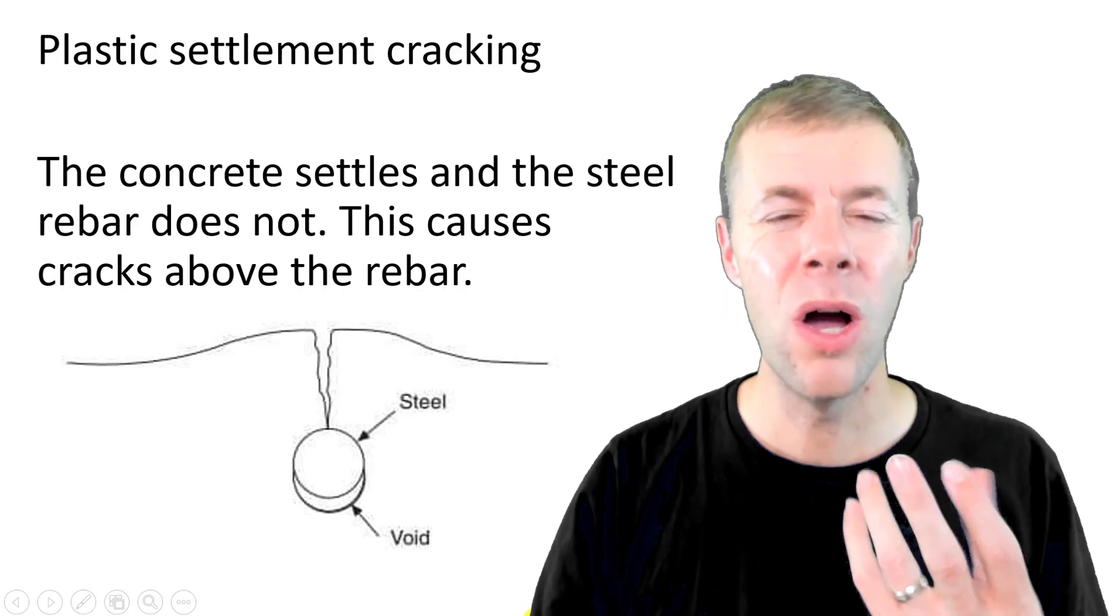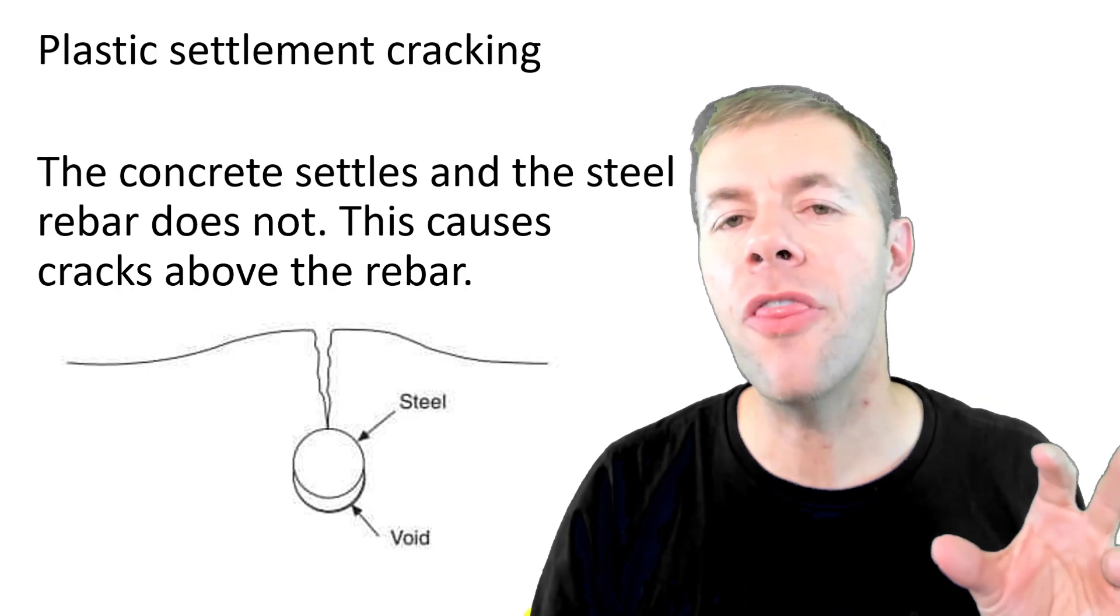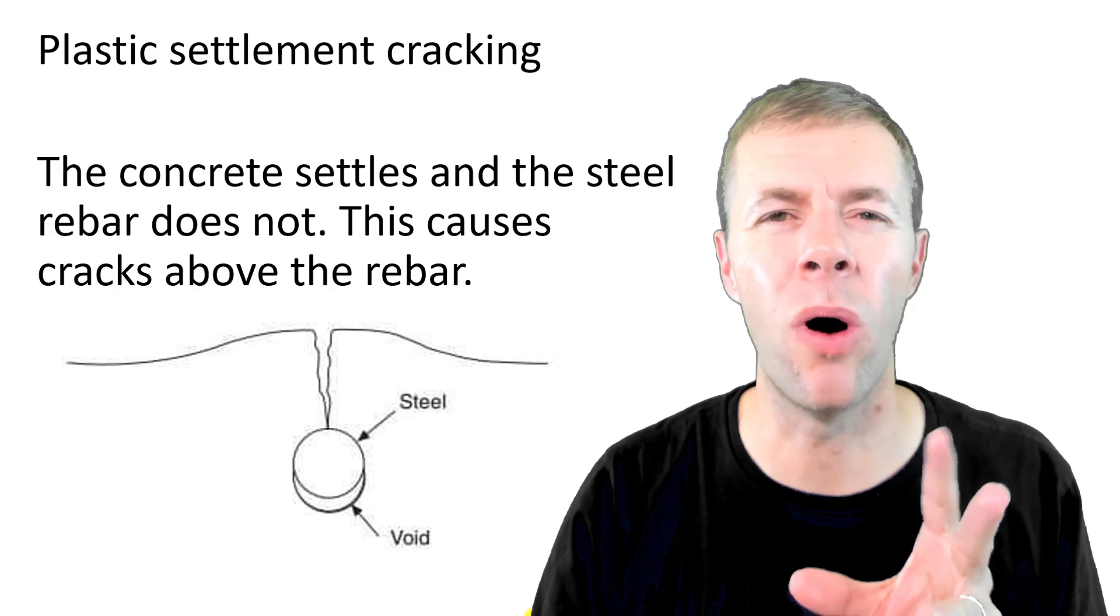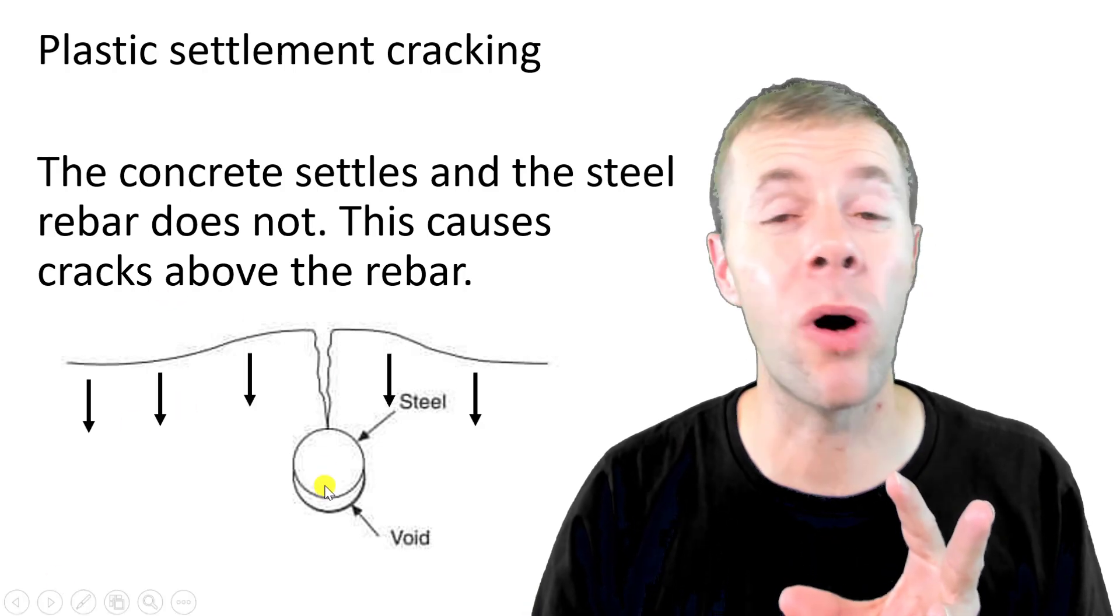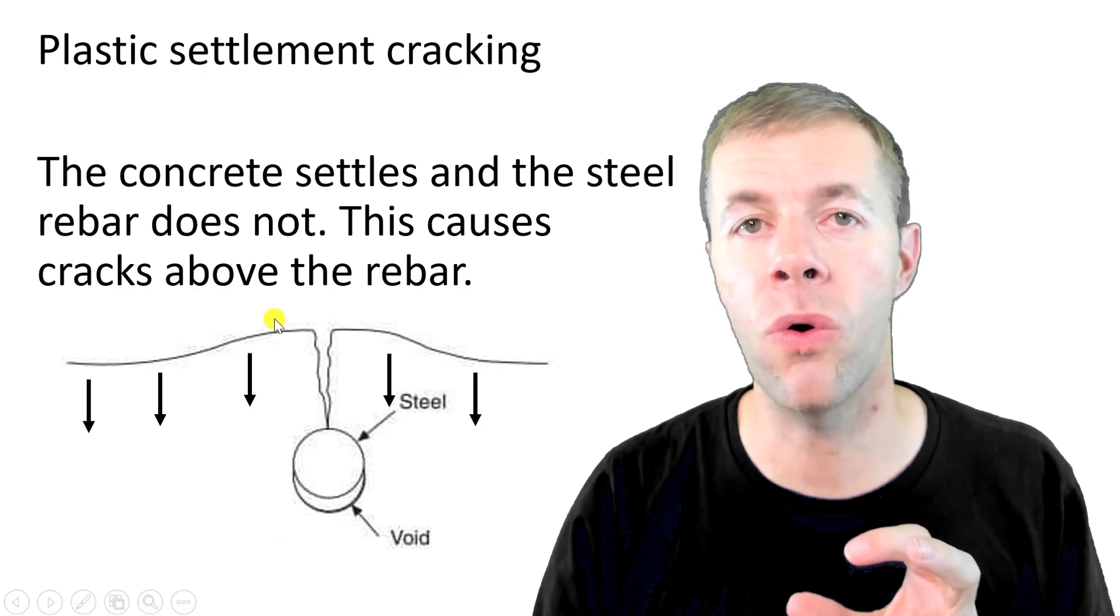How does this work? One cause is when the concrete settles and the rebar does not. This causes the cracks above the rebar. I'm trying to show it in this picture below. The concrete is going down, but the rebar not moving. It holds it there, causes a crack, causes a void. If we have outside chemicals, it has direct exposure to reinforcing steel. Not good.